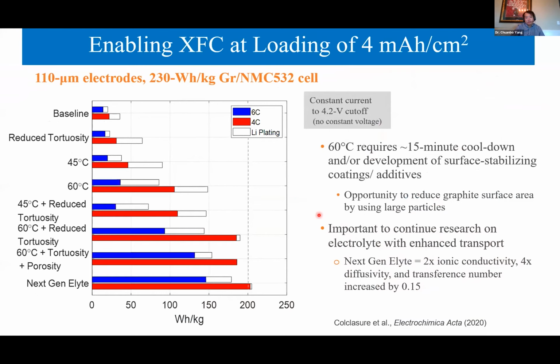Similar results can be realized for 4 milliamp hour per centimeter square and a non-conventional electrolyte at high temperature. But the temperature is not 45 degrees Celsius. We need 60 degrees Celsius. 60 degrees Celsius would require development of suitable coatings and electrolyte additives. Again, it's important to continue research on electrolytes with enhanced transport, something like 2 times ionic conductivity, 4 times diffusivity, and a transference number increased to 0.15 will be ideal.